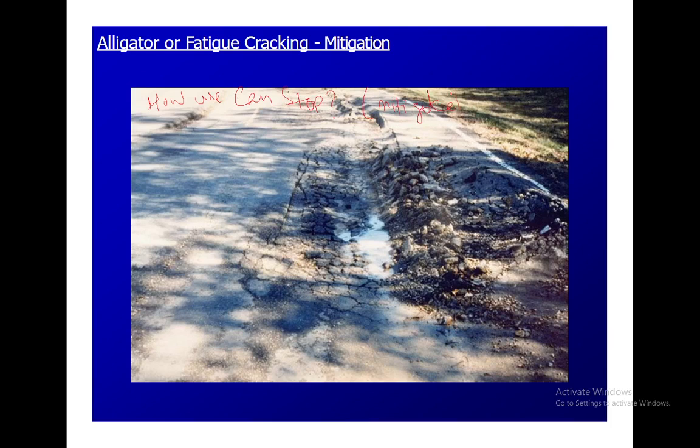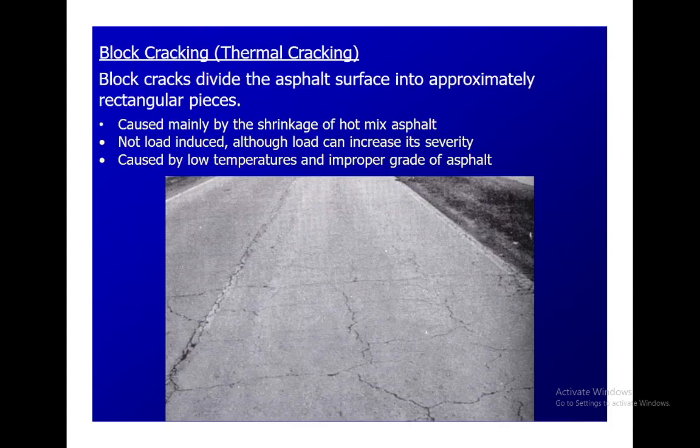Filling alligator cracks with a patching product only offers a temporary repair solution. The area where alligator cracks occur should be socketed and the base course removed, inspected, and corrected depending on the type of cracking present. We need to investigate if fatigue cracks have damaged the supporting layer down to the sub-base or subgrade. If the full depth is damaged, we need a Type D maintenance strategy to rehabilitate the whole road. If only the HMA is damaged, we socket and replace only the HMA.